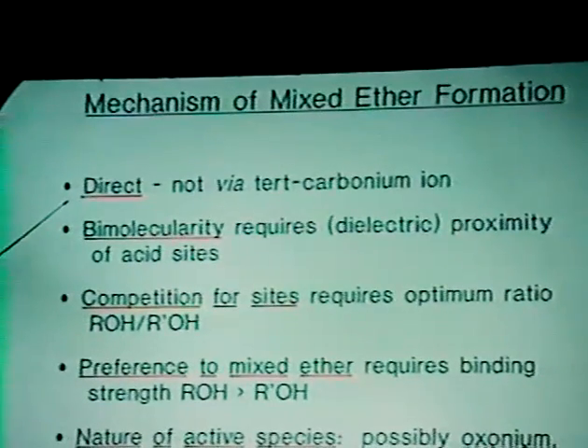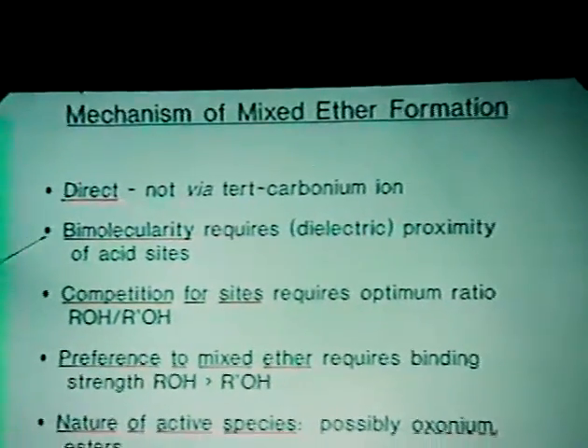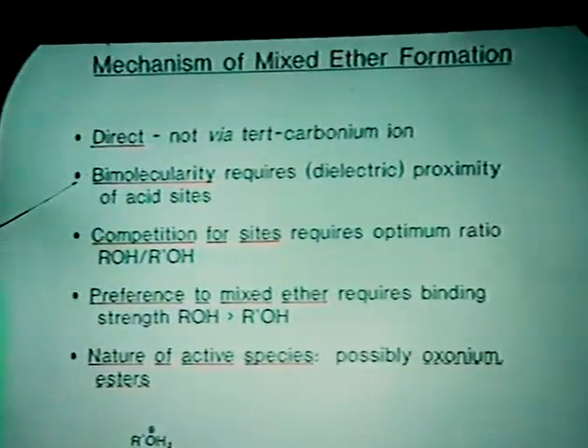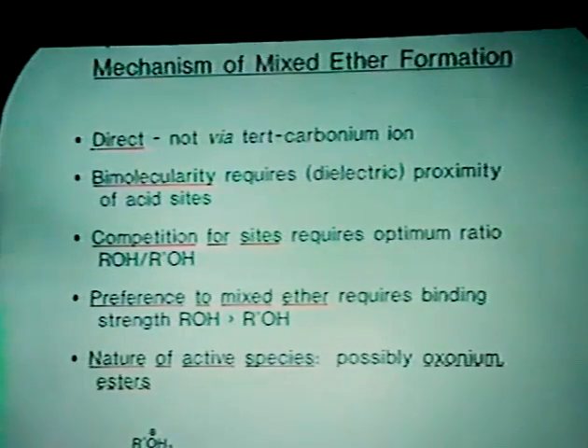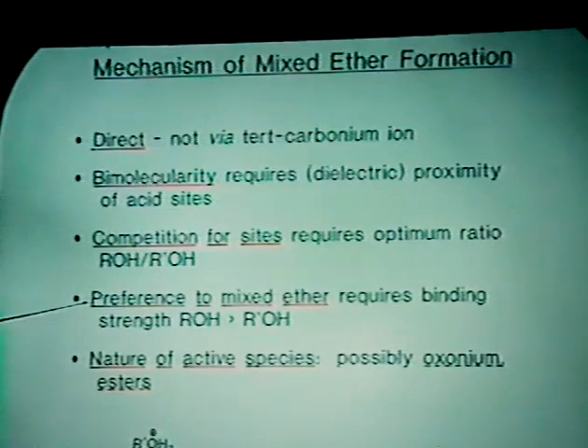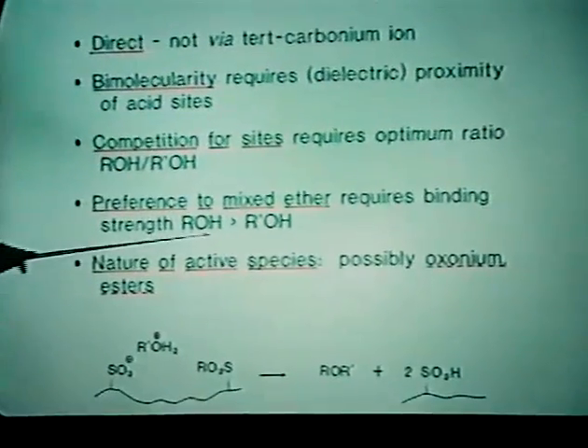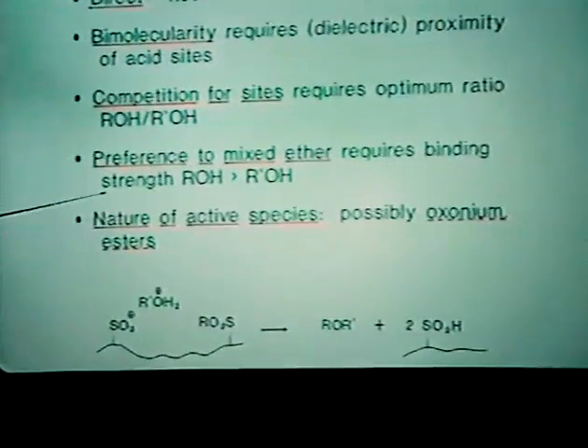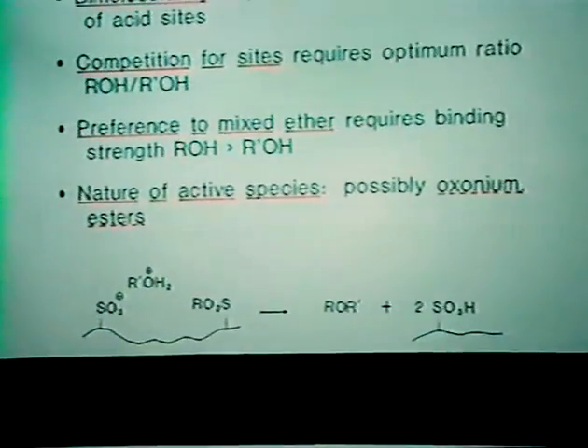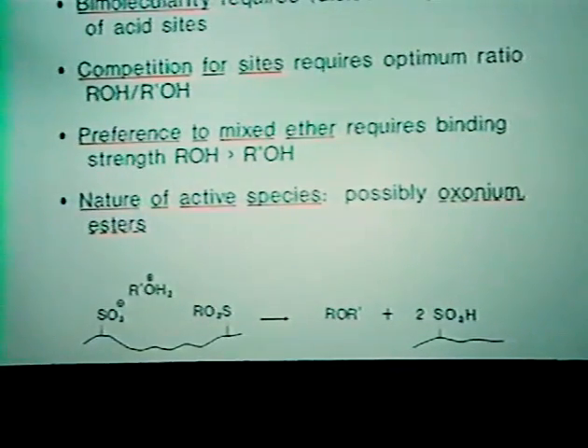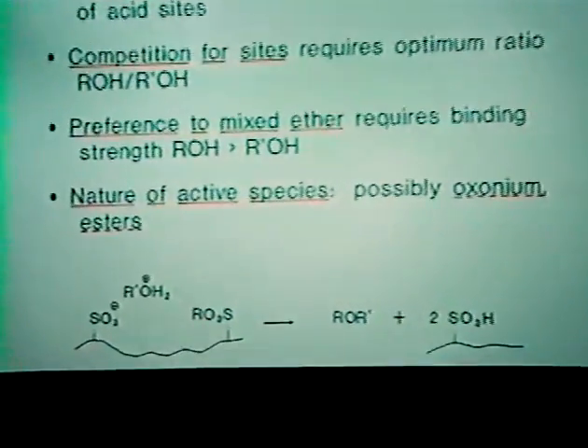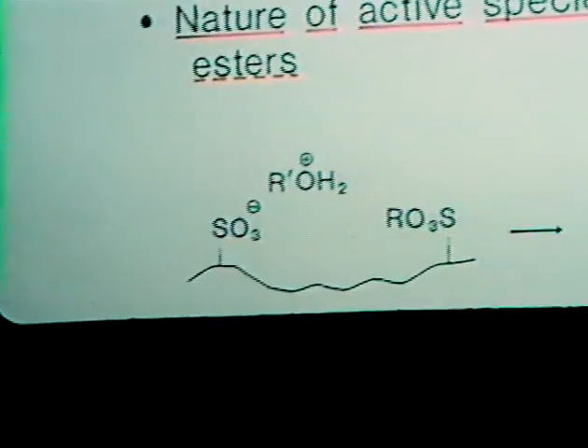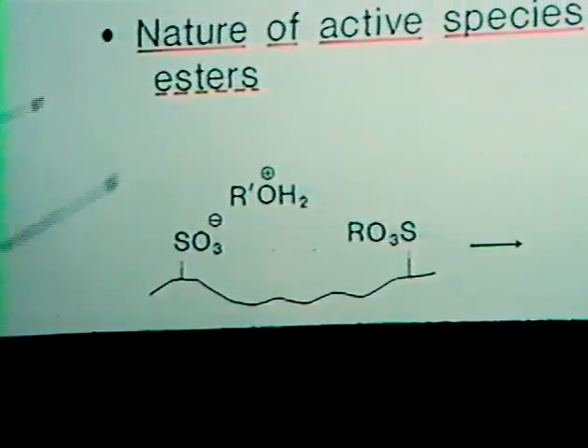The mechanism of coupling of these two alcohols is direct. We know that it's bimolecular. The theoretical curve there was a Langmuir curve in which there was a product of partial pressures of the two alcohols. We know that there is a competition of the sites, and we know that there's a preference, if we call R isobutyl and R prime methyl, to the mixed ether. We know that the active species cannot be carbonium. So what occurs to you is that it's oxonium, but if we have two oxoniums, how do they combine to an ether? That is not written in any organic chemistry textbook.